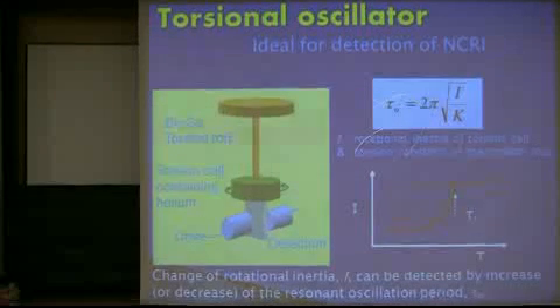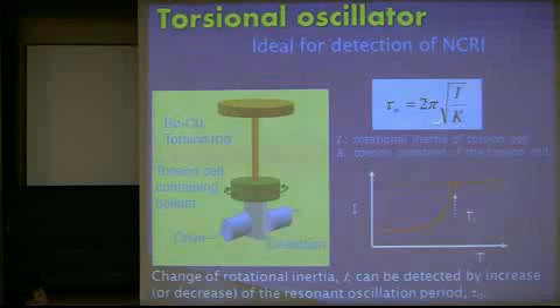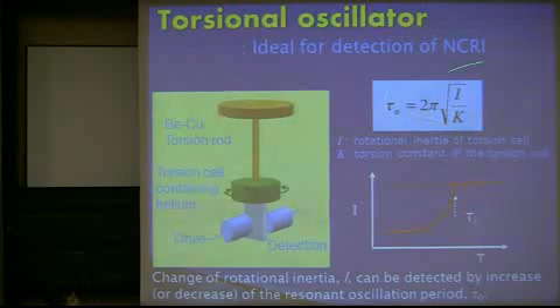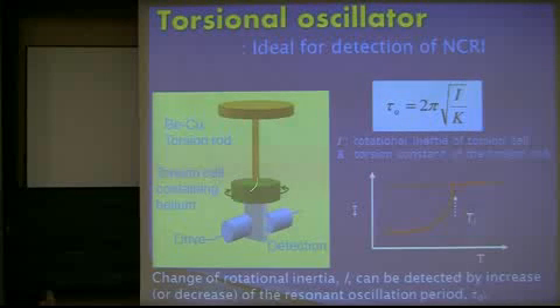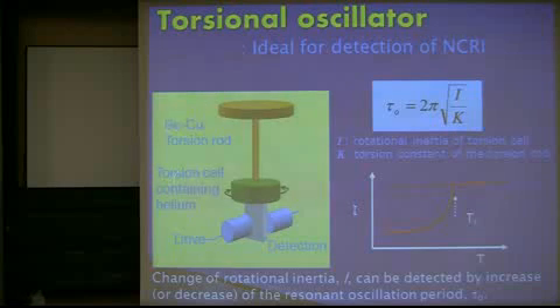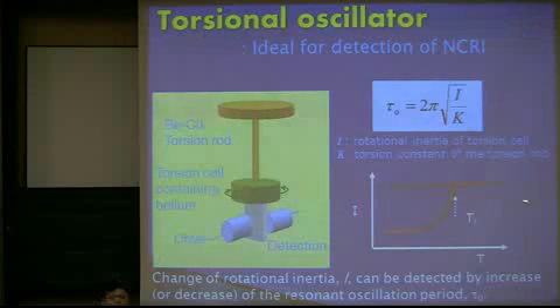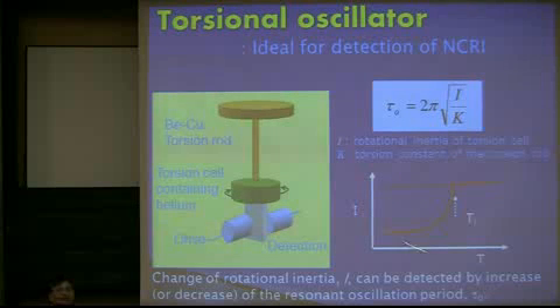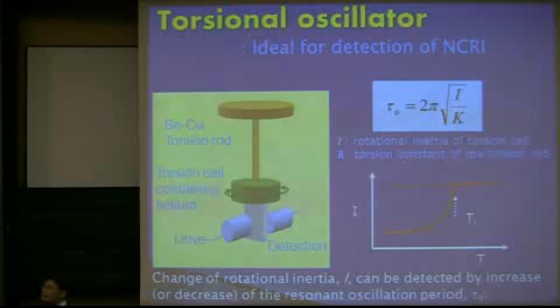Okay? In that case, you have the mechanical resonant period given by this equation, which is proportional to the square root of I over k. Here, I is the rotational inertia of this torsion cell containing helium, and k is the torsion constant of the torsion rod. So if you have a larger rotational inertia, or a smaller torsion constant, then you have a slower oscillation, so the resonant period increases. Okay? Good. So if you measure the rotational inertia as a function of temperature, when you decrease the temperature below the transition, there is a missing rotational inertia because of the appearance of non-classical rotational inertia. So you can measure this kind of change in the rotational inertia by measuring the resonant period precisely.